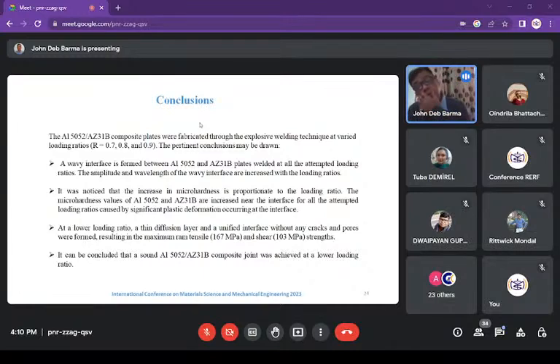It was also noticed that the increase in microhardness is proportional to the loading ratios, as we have seen in the graph. The microhardness values of aluminum 5052 and AZ31B increased near the interface for all the attempted loading ratios, which was caused by the significant plastic deformation occurring at the interface.